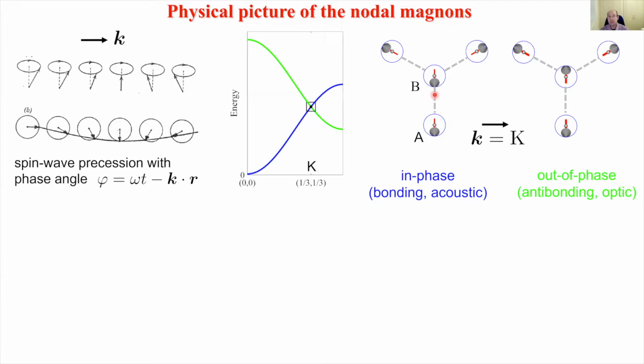Now, the spins in the other sublattice, on the B sublattice, in projection, can be either parallel or anti-parallel, meaning that we have an in-phase or out-of-phase magnon, acoustic or optic. And precisely at the corner of the Brillouin zone, where the angle between the A spins is 120 degrees, the interaction with the spin up here for the perpendicular component cancels, because all of these are pointing at 120 degrees away from each other. So these two states are degenerate. This spin can be either parallel or anti-parallel, and in principle can be in any direction. The energy is exactly the same.